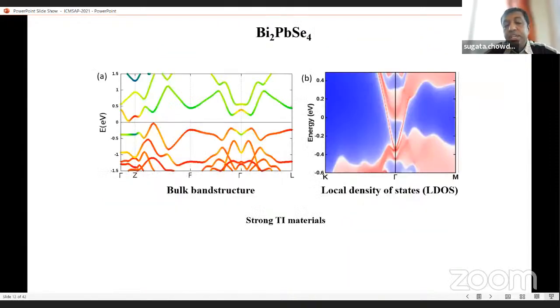So what we did, first we found out whether a non-magnetic septuple layer is possible or not. We noticed that at the gamma point we are getting band inversion, and this is the local density of states for that material, and it shows the formation of the Dirac cone of the manganese bismuth lead selenide system.